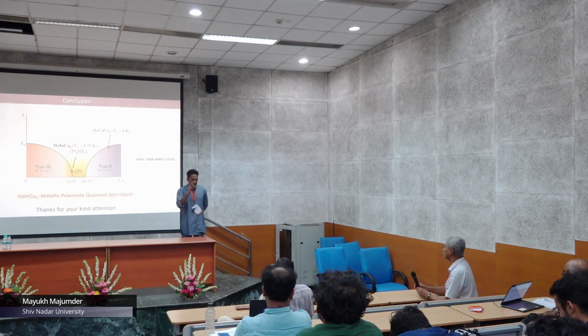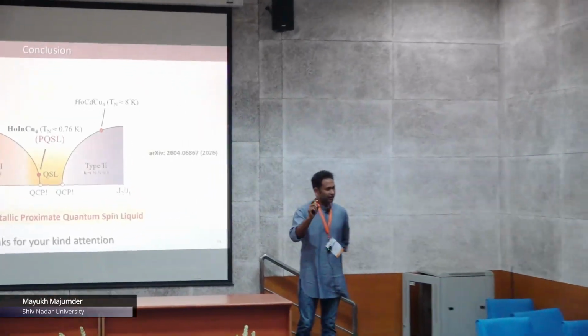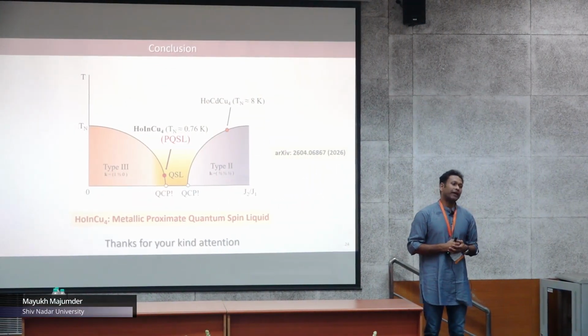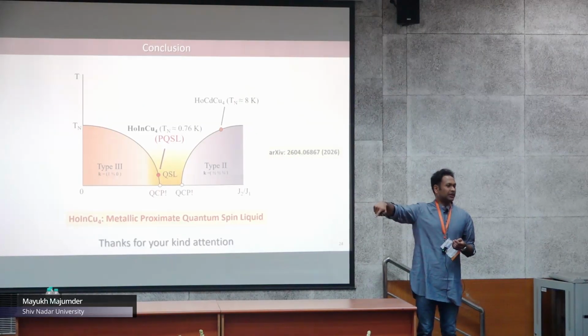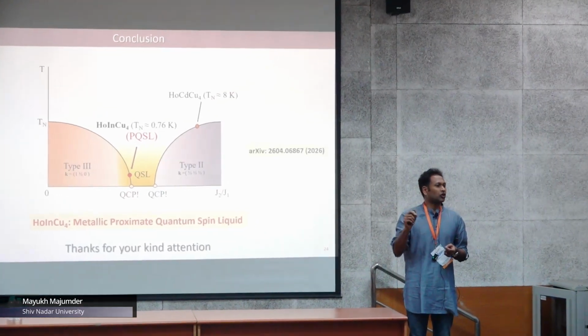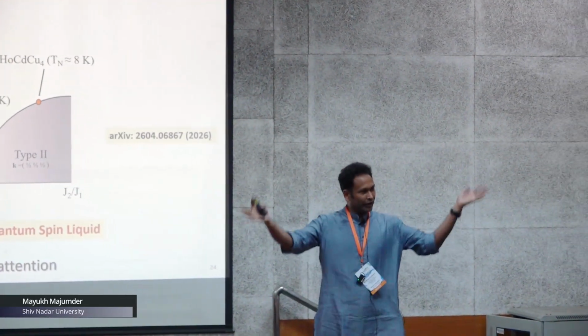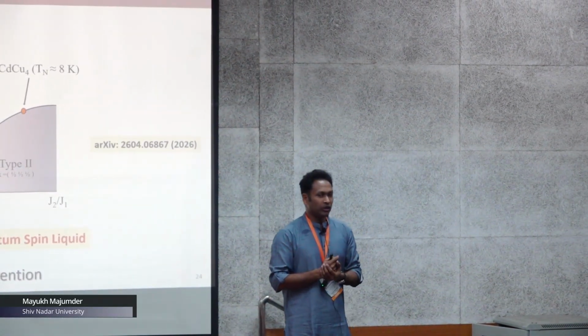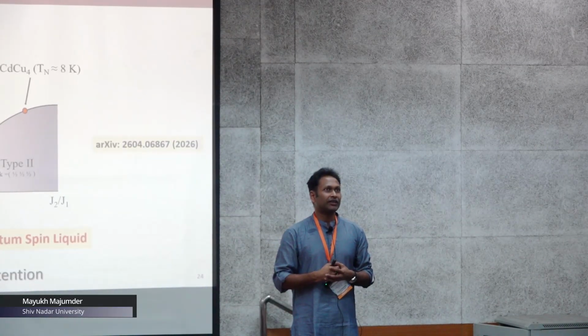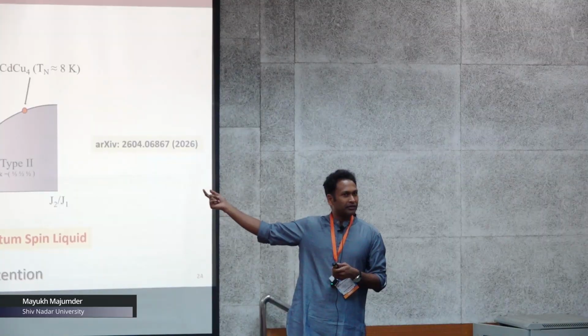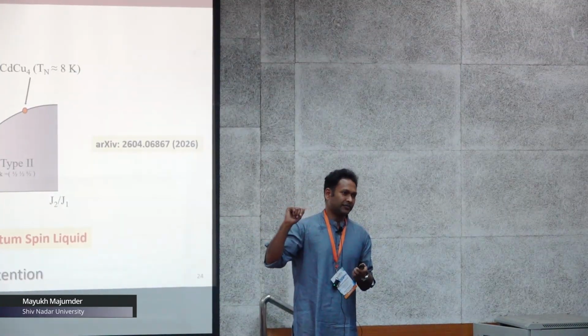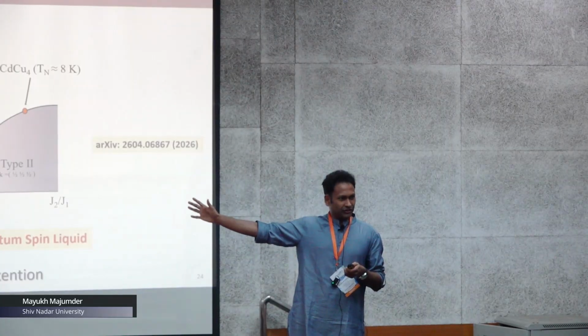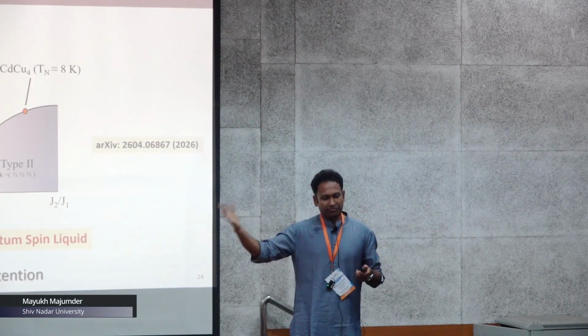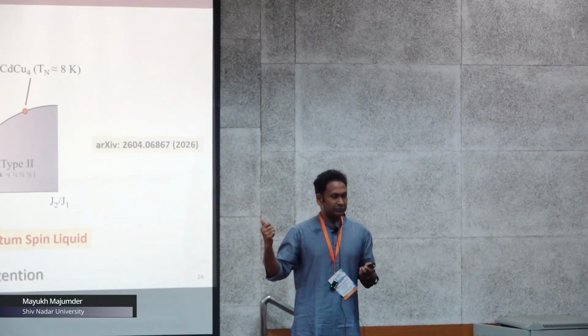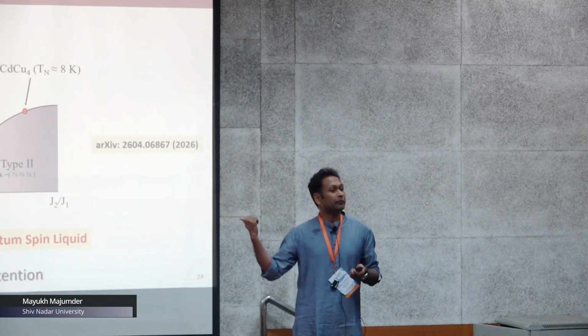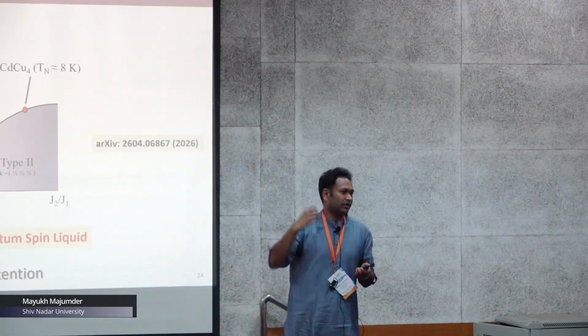Okay, so the range μSR can detect, the full spectrum, depends on the gyromagnetic ratio of the muons, along with the radioactive decay of the muons. As you know, it is of the order of 2.2 microseconds. So around that value, whatever excitations are happening, you would be able to know. And the gyromagnetic ratio is 135 megahertz per Tesla. That's why the relaxation rates we showed are of the order of microseconds. So we are in that range. Since we are dealing with dynamically fluctuating systems, it can happen that a system is dynamic on the muon time scale, but not dynamic on neutron or NMR or other time scales.